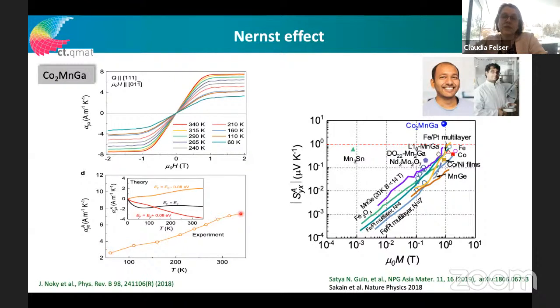And if you know the TC of this material, which is like 800 Kelvin, you can expect that the value will go even up to 8 to 10 or 12, which is much higher than what you would normally expect. It would lead to a higher figure of merit than normal thermoelectric materials. So you can simply compare it here to a figure which was also done by our Japanese colleague. It's much higher than what you expect, as a function of the magnetization.